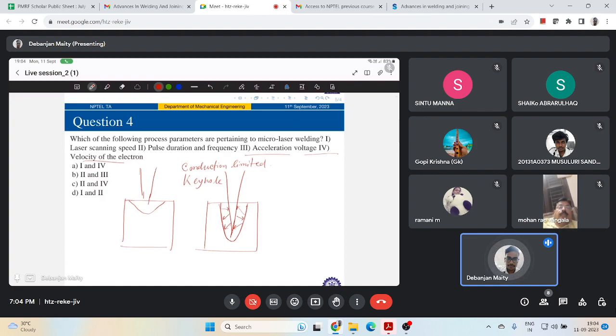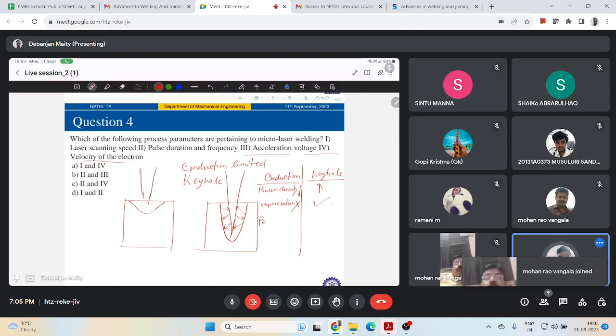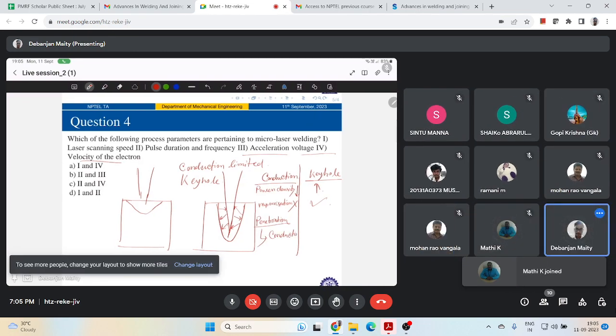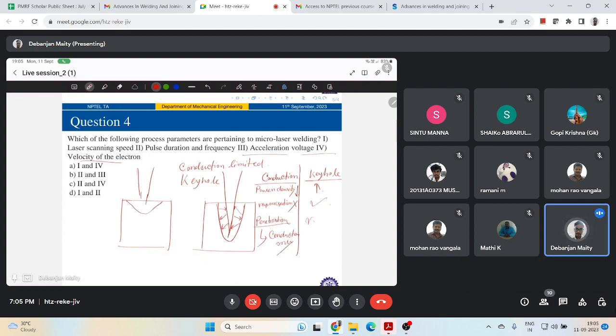So in terms of differences, let's say this is conduction mode and this is keyhole mode, right? One is your power density: this is less, this is more. Then you have vaporization. Here it doesn't vaporize, here it vaporizes. Then in terms of penetration, this is controlled by conduction only. Here you have vapor pressure from the hot metal, which keeps that blind hole open during the welding.